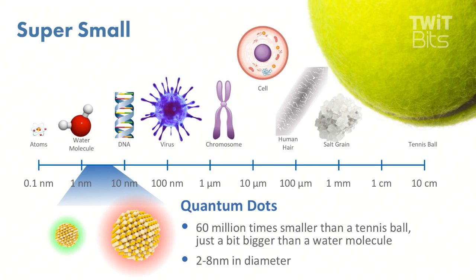In this graphic you see two different sizes of quantum dots — those will have different optical properties. The larger ones, if they emit visible light, will emit red light — very discrete red light. The smaller ones will emit blue or green light. You can make these whatever size you want; you can carefully control the size and thus carefully control the color.